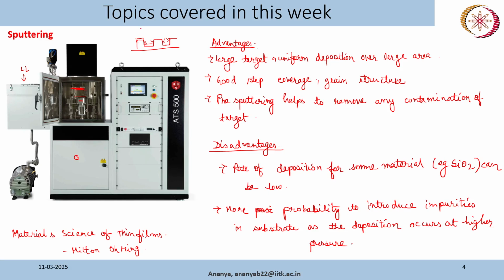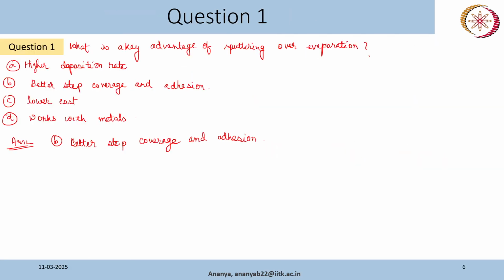But sputtering is not directional. It can be an advantage. When we want a good step coverage, if we have a very conformal kind of structure, we'll get a good deposition using sputtering. Also, high energy atoms hit our substrate, because these are ejected material due to sputtering. So the adhesion between the film and the substrate will be better compared to evaporation. So this is the main advantage.